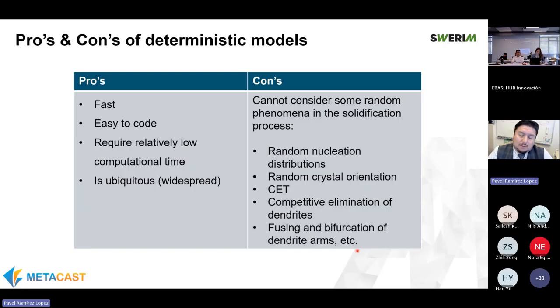What we saw, for example, in the videos this morning about competitive elimination of dendrites, and how the solidification fronts collide and form grains in very peculiar ways that, for example, are a function of the flow, in the slab, in the corners, or in specific areas of a component, this level of detail we miss. So we don't get this information on grain evolution. We have an average grain size.